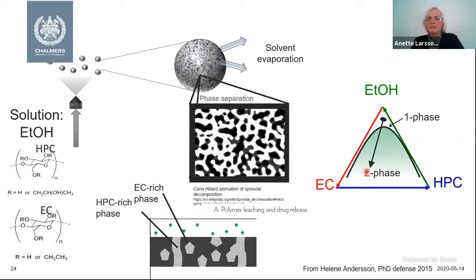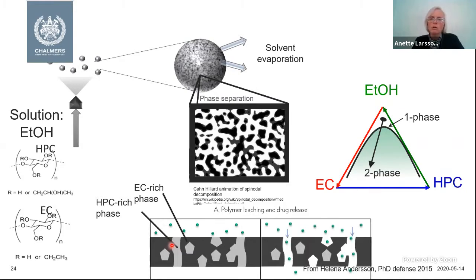individual domains where you have nucleation and growth, and they are not connected to each other, then you will have very slow release. And the reason for this is that the drug release is controlled by the coating layer, which has one phase of the EC and the HPC phase. And when we place it in water, the HPC phase will start to dissolve, and then you create a pore, and that pore can be used as a channel for the drug to be released through.